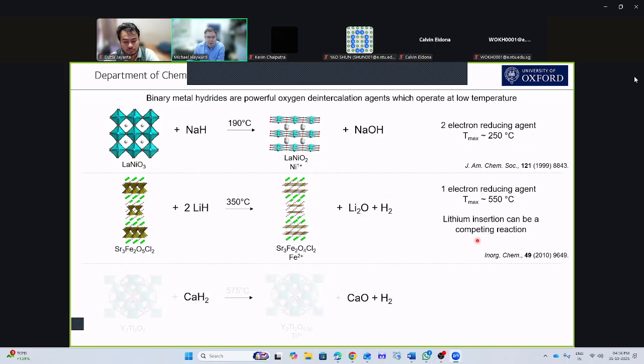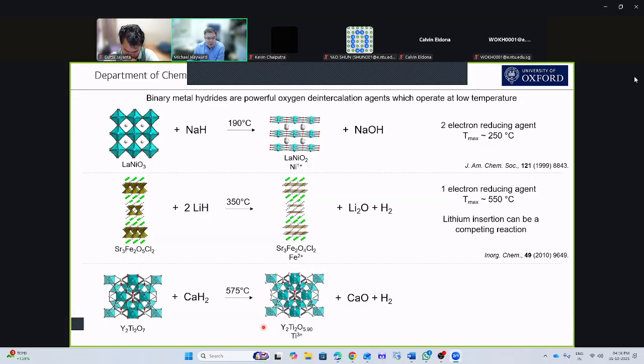And the third and probably most versatile of the hydride reagents is calcium hydride. So calcium hydride extracts oxygen by making calcium oxide and hydrogen. And here's the example we've already seen. And now calcium hydride is stable up to about 850 degrees C. So we can really explore extracting some rather immobile oxide ions from our complex oxides.